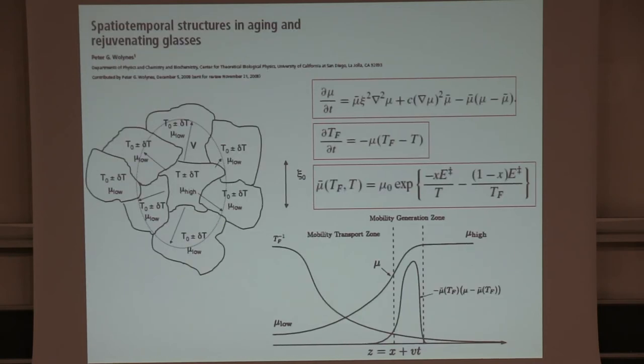How do you figure out what really goes on in real glasses then? They're not equilibrium systems. They're not even quite frozen systems. They continue to age. Well, you actually have to throw back the activated events into a full dynamical theory. And I've run out of time, but that full dynamical theory has a large number of interesting consequences, one of which is if you do experiments of heating things up rather than cooling them down, then these regions expand like a flame rather than just sitting there. So this rejuvenation experiment involves a front propagation, and that's something that's also been seen when ultra-stable glasses were made by Edgar. This theory predicts very well the speed of that front propagation.